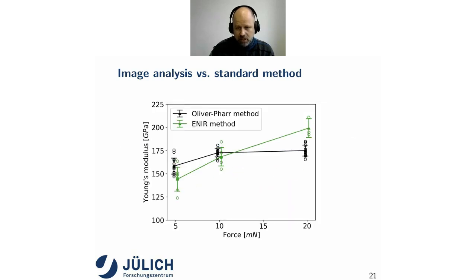Now, next to the hardness, you can also look at the Young's modulus. At small forces, we are pretty precise compared again to the Oliver-Pharr method. However, at larger forces, we definitely overestimate the Young's modulus of silicon, as in this case. But I should also mention that silicon is definitely one of the more difficult materials to use because it's rather hard, it's rather stiff, so the contact area is rather small, and these evaluations are quite troublesome.